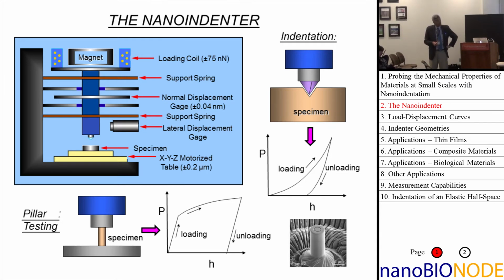And also withdrawing. The basic idea here is that the force displacement curve can be measured down in the nanonewton range, and the displacements can be measured down in the angstrom range with some of these devices now. And so you can get force and displacement information, and the idea is that there is a whole lot of stuff in that curve that can be measured from nanometer and micron size contacts that tells you things about the mechanical properties of the material.